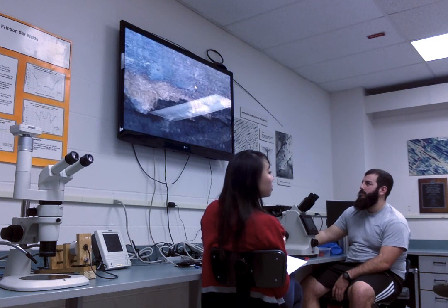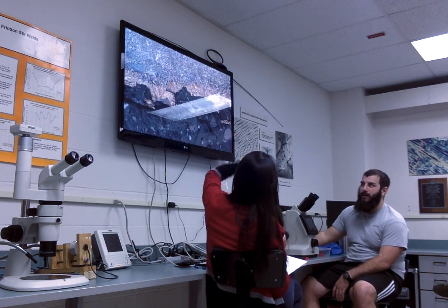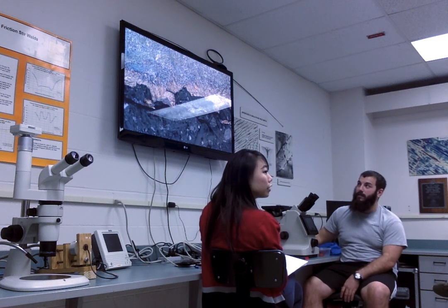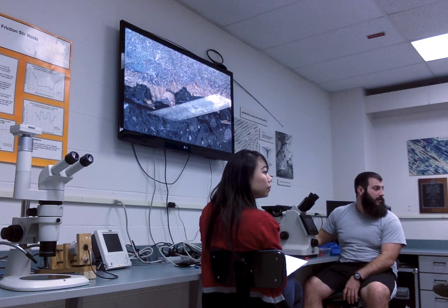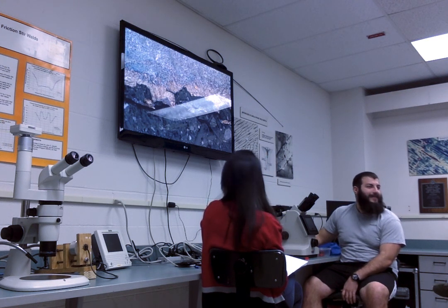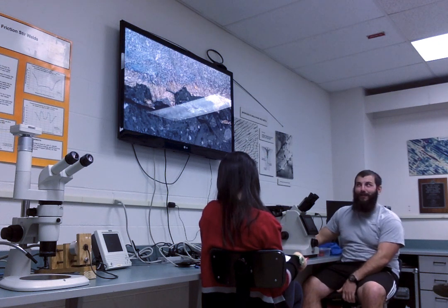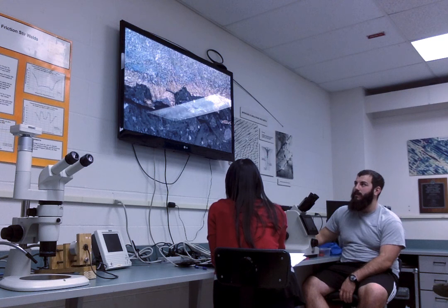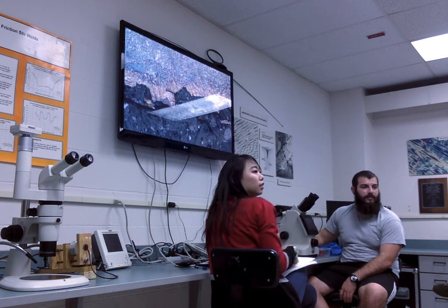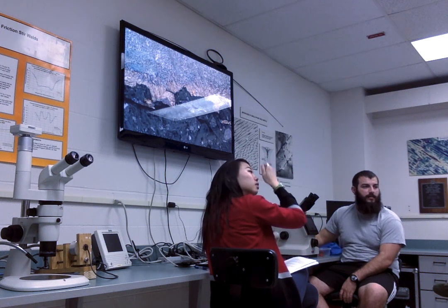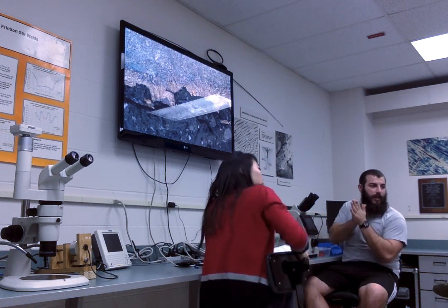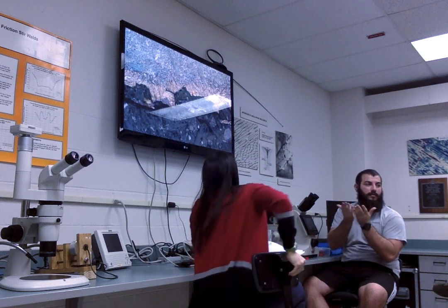When it's hard to tell, you kind of base it on how jagged it is, usually. So does anyone see transgranular now? Yeah, you can pretty confidently tell that it's intergranular and not transgranular, right? Yeah, a little square. Put this in your lab report. He was saying that this one looks transgranular, I think. How can you tell other than being straight? It's like cutting right through the grain. So slap them together. The crack wasn't there. They should almost line up.